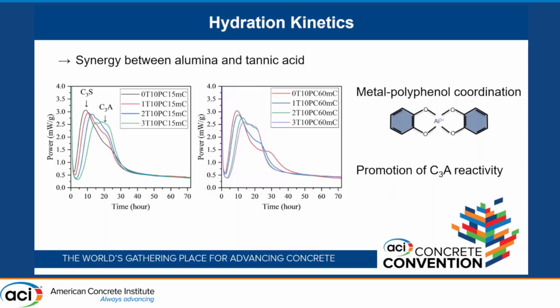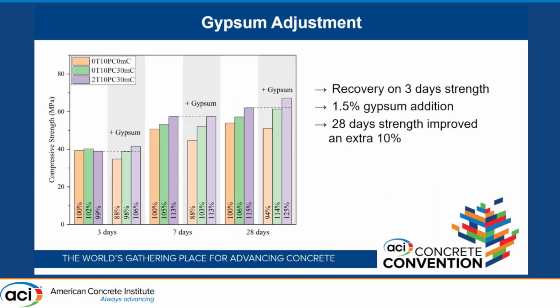And then we thought, well, maybe we can take this a step further since we're seeing some interaction with C3A. Why not also adjust the gypsum content? That might help. And surely enough, we're able to improve the performance even further. You can see that problem we had at 3 days where you're just above 100%, now you can bump that strength to 106. And now instead of 15% at 28 days, you're able to achieve 25% at 28 days, which is very good.